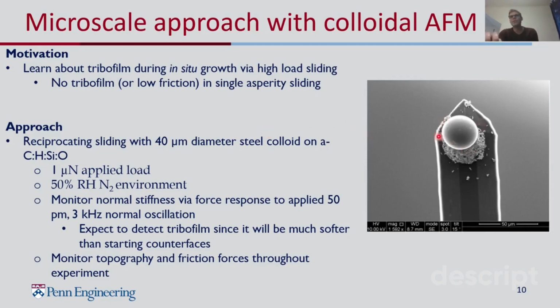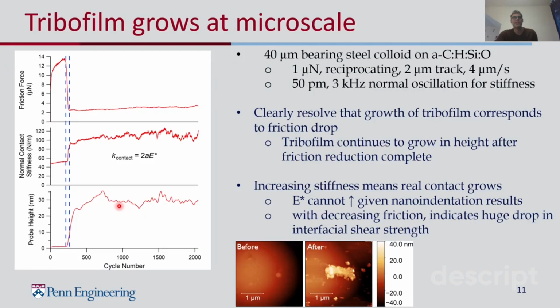To do this, we used a steel colloid and we glued it onto the end of an AFM cantilever and then did more experiments in the AFM. In this case, we do reciprocating sliding akin to what is done in a tribometer. So this gives us the advantage of being able to monitor multiple signal channels. So we have obviously the friction force, but we also were able to monitor the topography. And finally, we also imposed a normal oscillation on the tip. And then by measuring that force response, we can calculate what the normal stiffness of the contact is, which is useful for seeing any changes that might be occurring due to perhaps the formation of a tribofilm, given that we expect the tribofilm to have a much lower modulus than the starting material.